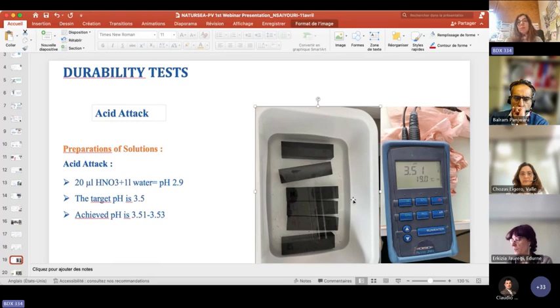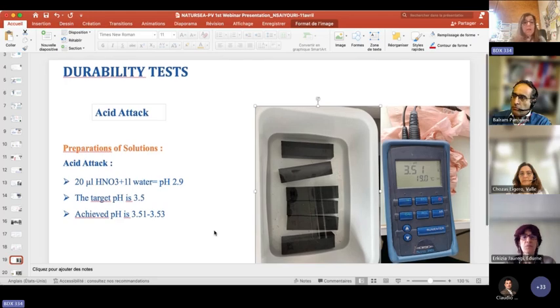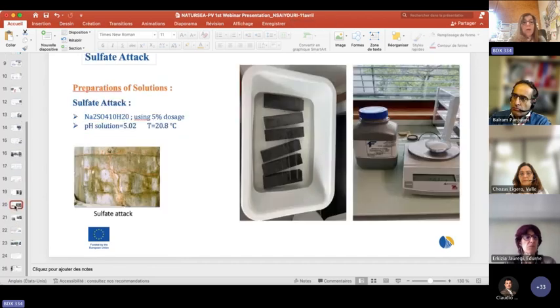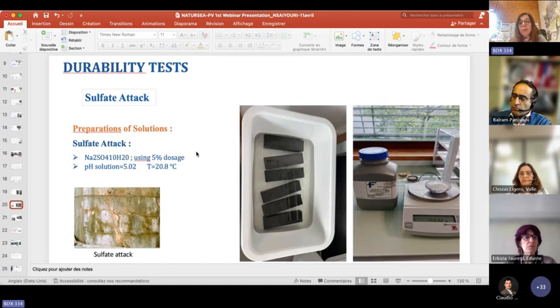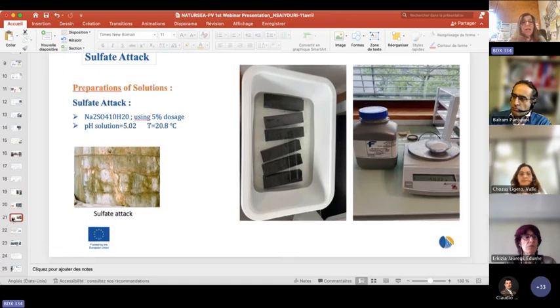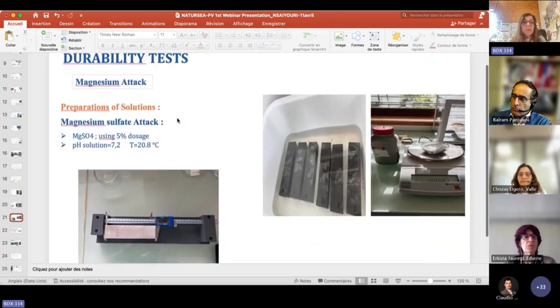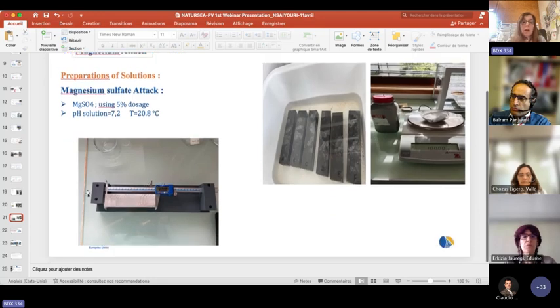Now I move to durability tests. In fact, we started the durability tests, but as it's not a very old test, it's only about 2 months. We are now not seeing real degradation of our specimen, but we are doing standard tests like acid attack, sulfate attack, following the standards, and also magnesium sulfate attack, which is the third one. We are following the mass and the dimensions of the sample, but also non-destructive tests.